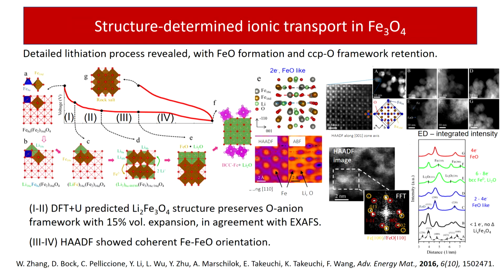So to begin with, we need to start with the atomic molecular level to understand what really are the reactions of magnetite. And this is some lovely TEM work in collaboration with Feng Wang at Brookhaven National Lab, demonstrating that we start with Fe3O4. There's initially a lithium insertion reaction. Then we move to FeO, finally to iron metal, lithium oxide. And what's important about this work is that the oxygen anion framework is largely retained. So it's possible that the retention of that oxygen anion framework is part of the reason that these systems are reversible at all.